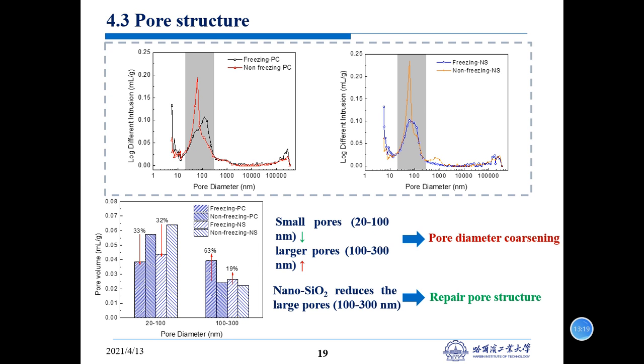the deterioration of the pore structure, and according to the pore size distribution, we further show the pore volume between 20 and 300 nanometers. We can see this figure. We can see the small pores decreased, and the larger pores increased. That means the pore diameter increased, and we can also see the nano-silica reduces the larger pores. That means the nano-silica repaired the pore structure.